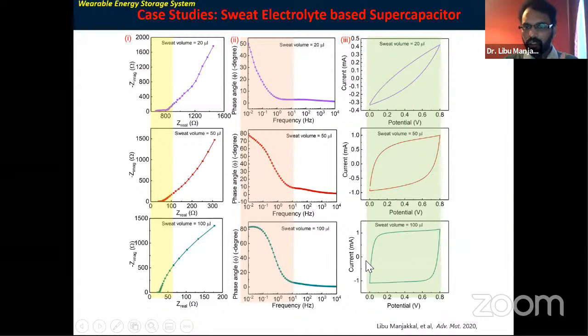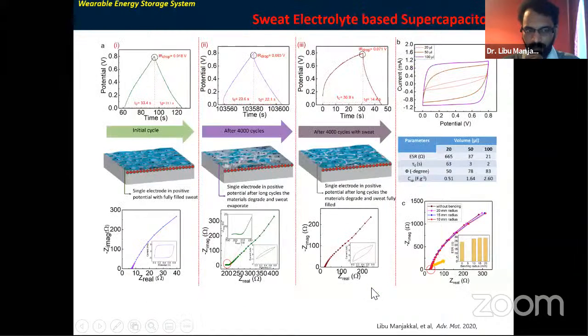And you can see when the volume of sweat is very low, depending on the size of the device, okay? Here I took an almost 5 centimeter square area device, and depending on the size and volume of the electrode, I noted that when you have a very good volume of sweat, it gives a very good performance. For example, with 100 microliter, it easily distributes around the electrode, and the device shows a very good current density and performance.